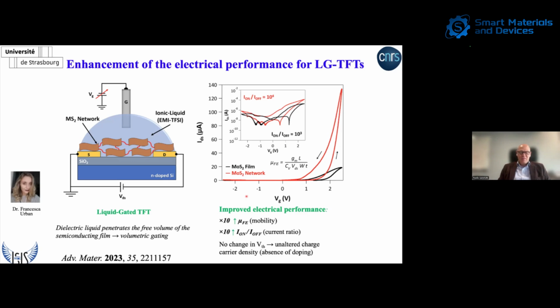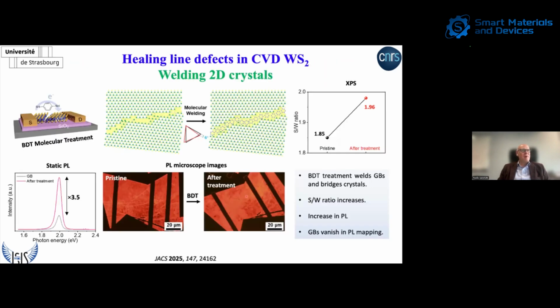Now, another example of this benzene dithiol is something that we have reported recently, again by Bin An, which was addressing another type of defect that you commonly have in two-dimensional materials, and these are line defects. Line defects that you have in particular in Scotch tape or CVD type of crystals. And here we focus our attention on tungsten disulfide, just to show you again that this approach is broadly applicable to different types of disulfide, diselenide, and ditelluride materials. So the idea was pretty simple: CVD crystals can have this kind of line defect, and we decided to use the benzene dithiol in order to weld this defect, so to connect the two adjacent crystals. Of course, doing that, you increase the content of sulfur versus tungsten within the film.